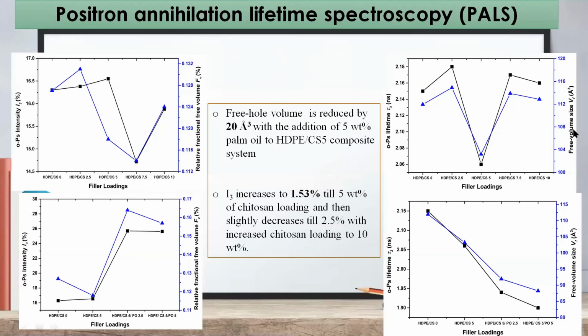The technique operates on the principle that a positron or a positronium will annihilate through interaction with electrons. This annihilation releases gamma rays that can be detected, and the time from emission of positrons from a radioactive source to detection of gamma rays due to annihilation corresponds to the lifetime of the positron. In molecular materials, the lifetime of orthopositronium is environment dependent. There are two positroniums, the parapositronium and the orthopositronium. Orthopositronium is in the triplet state with a characteristic self-annihilation lifetime of 142 nanoseconds in vacuum.